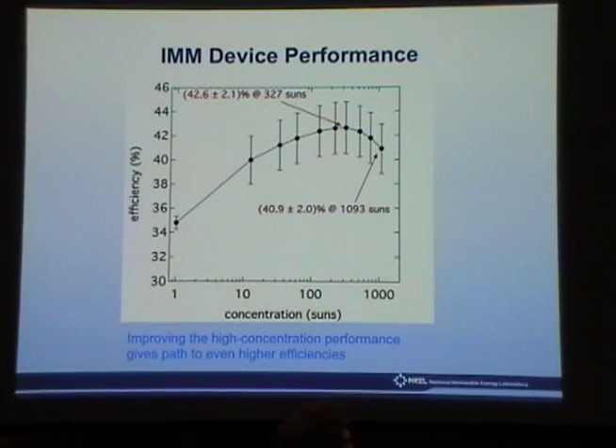So this is a graph of our best result at NREL to date. This is efficiency versus concentration. This is a device with one metamorphic junction, so it's got a 1 eV bottom cell. You can see, we're pretty proud of this result. It's 42.6% at 320 suns. And it maintained its efficiency all the way out to almost 41% at over 1,000 suns.